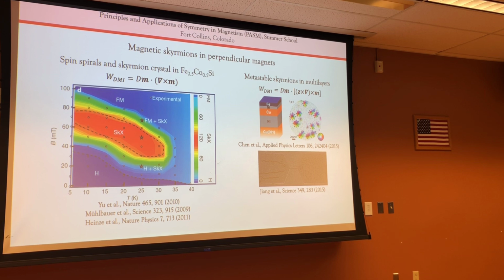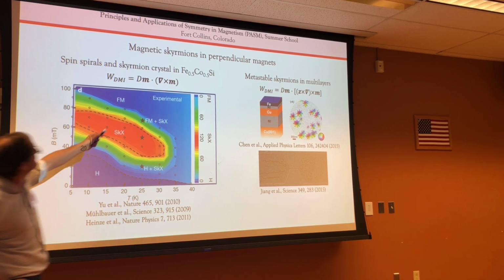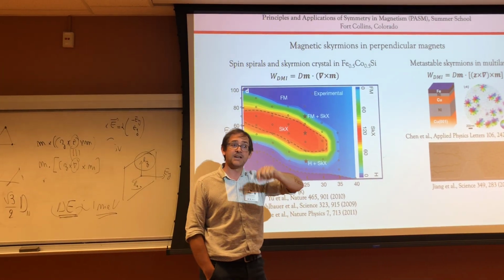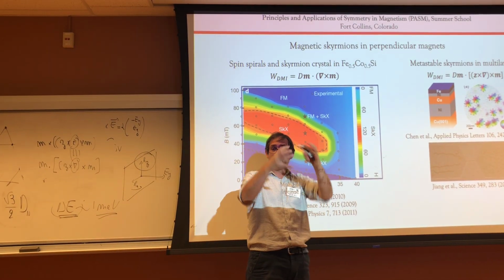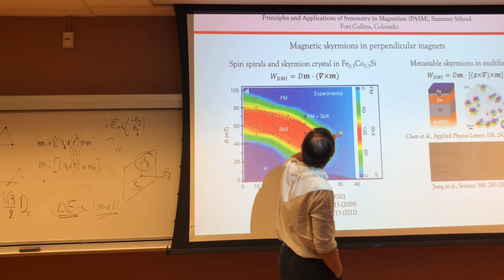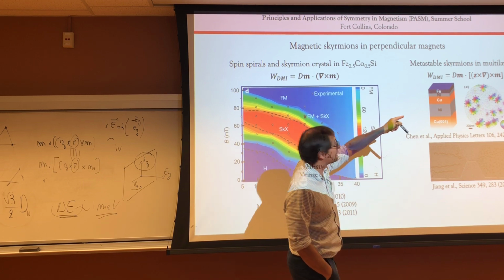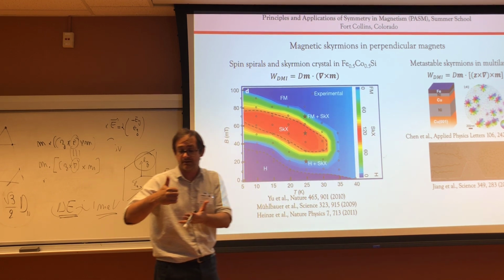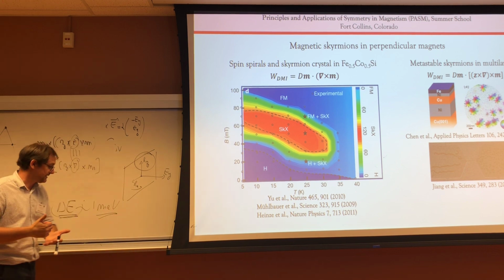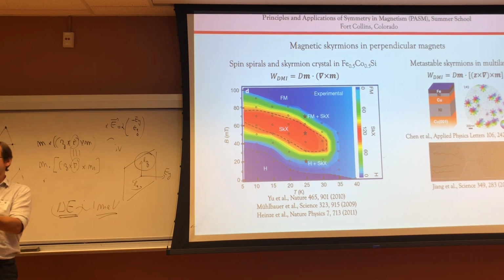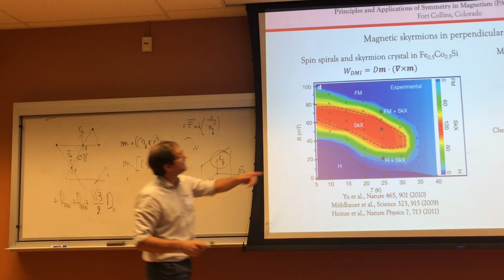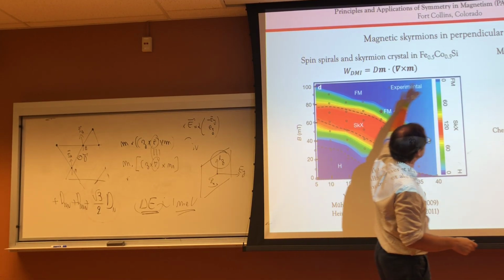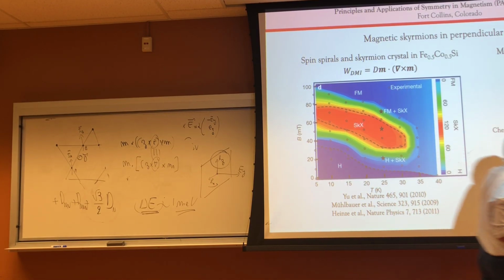Interesting. Now if you go for the B20, B20 has inversion symmetry breaking in the bulk. It has this cubic structure. So what you have is not a Z cross gradient, because there is no preferred direction. It's a cube. So X, Y, and Z are equivalent. And in this case, what you have is a gradient directly. It's not Z cross gradient, it's just directly a gradient.